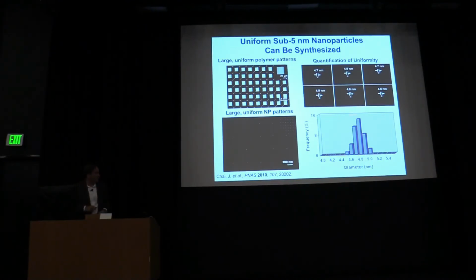I would argue this is more controllable than solution phase syntheses, and our group's developed some of the best solution phase syntheses for gold-based nanoparticles. So I think I can say that reliably. It's very difficult to get this type of monodispersion in any solution-based synthesis on this scale. I keep telling you that everything within the reactor goes into forming one particle. Well, if that's true, you then can begin to think about using this as a tool to understand how particles form.